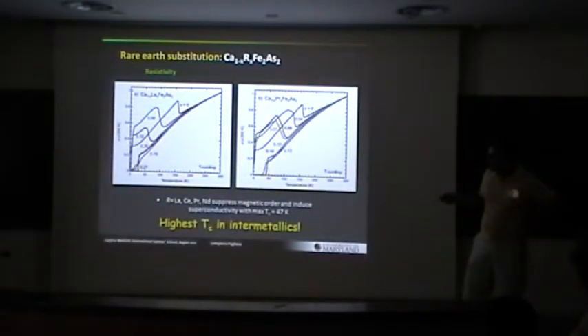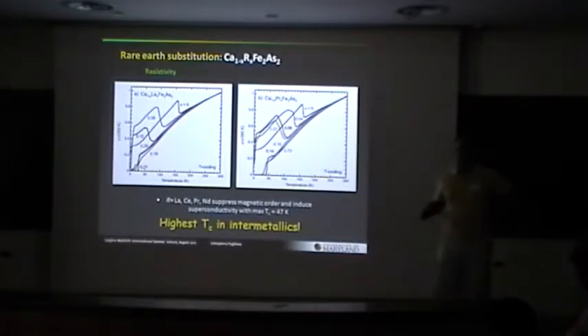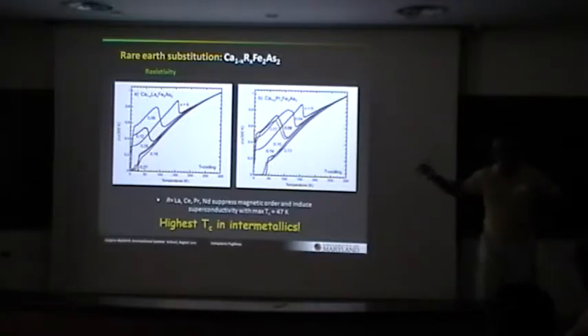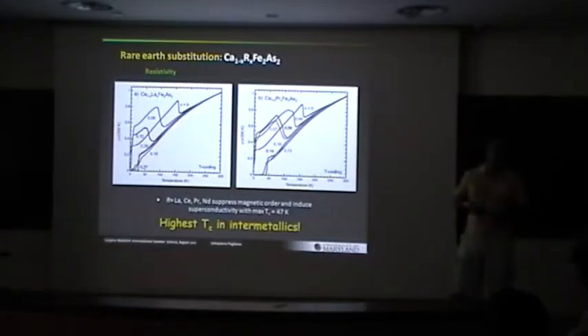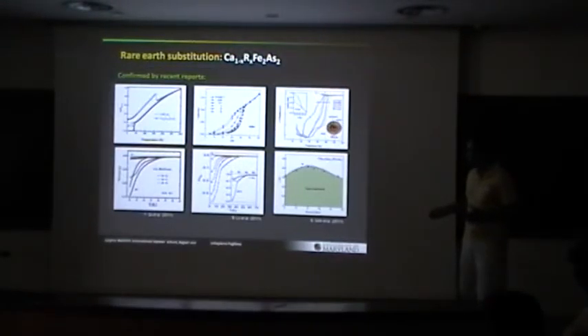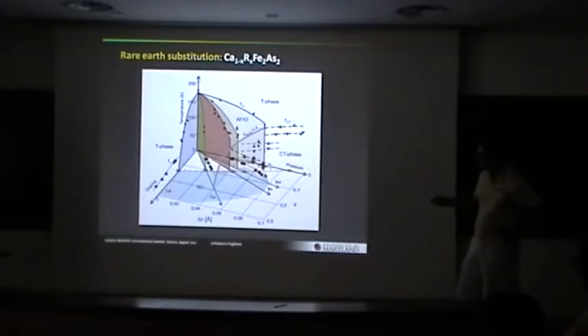In some samples, we actually see evidence of, you see this here, there's some indication of a small transition here, even 3 actually. There's something at 40, something at 20, and something at 10. So, while I don't want to say that there's 3 superconducting transitions in one sample, there's evidence of this 10K phase around, and that's why I think it's due to some strain. So we're in the process of doing annealing and all these kinds of studies to see how we can isolate one or the other. But I think that they're different phases. So in essence, I think the calcium 122, you have to dope it in order to get this higher TC phase. I think that's clear.